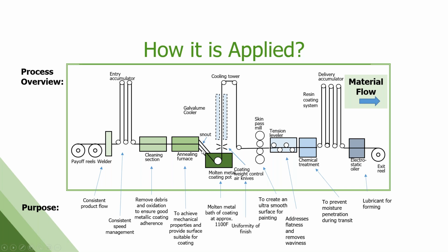The strip then moves down into this molten metal pot. This is where the metallic coating we're talking about gets applied. So this is at 1100 degrees Fahrenheit. It is the appropriate mixture of aluminum and zinc in liquid form. Strip moves through here. Coating gets applied to the strip. We have air knives, which blow on the strip that control how much of that coating is on the final product. Goes through a lot of cooling to let that crystallization process start and get good adhesion to the steel.